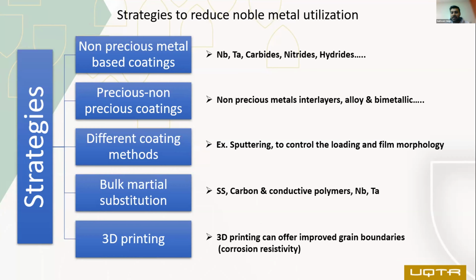No problem. So the electroplating method is a worldwide accepted method to coat the bipolar plates and the titanium porous transport layers. And electroplating is a very notorious method. It's very hard to control the loading of the precious metals. So what sputtering can offer is that it's very easy to control the loading during the coating of metallic components. We can even reach 1 nanometer, 2 nanometer, 3 nanometer with the help of DC magnetron sputtering or RF magnetron